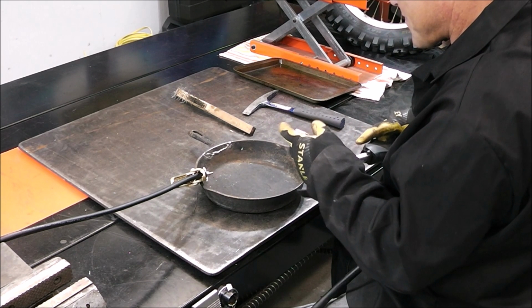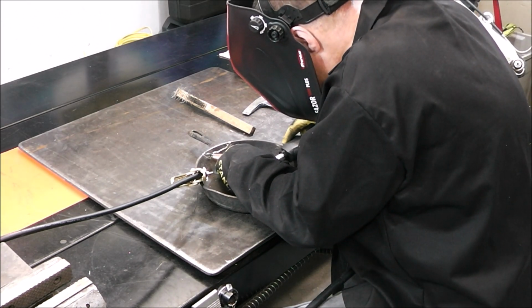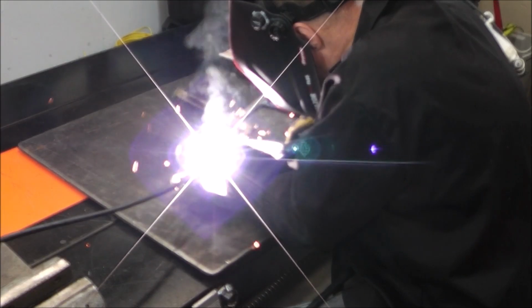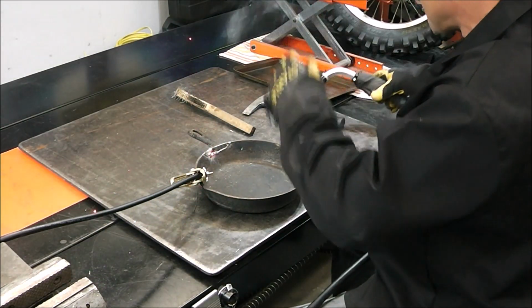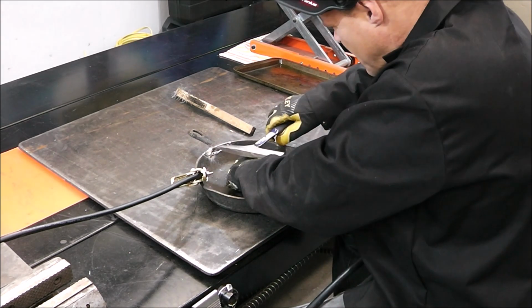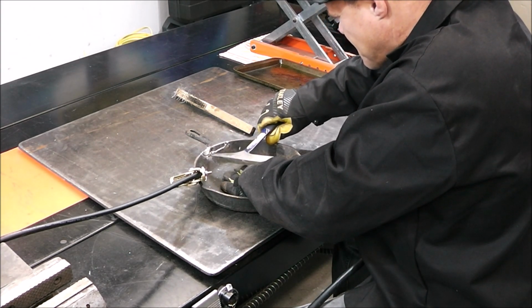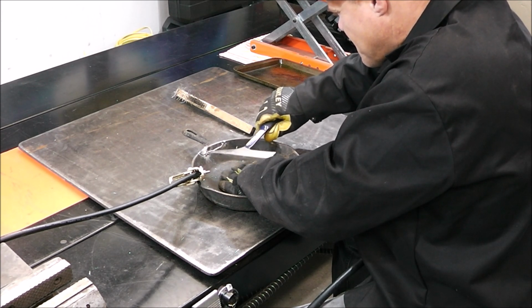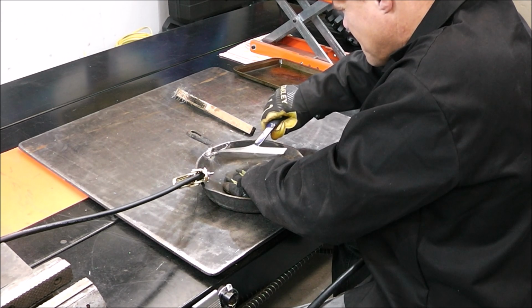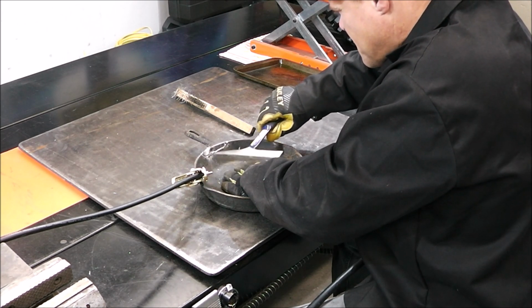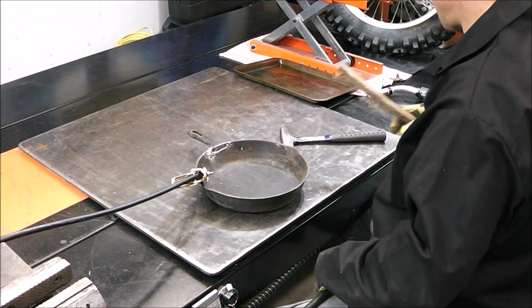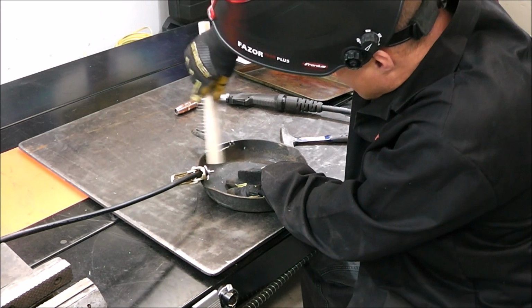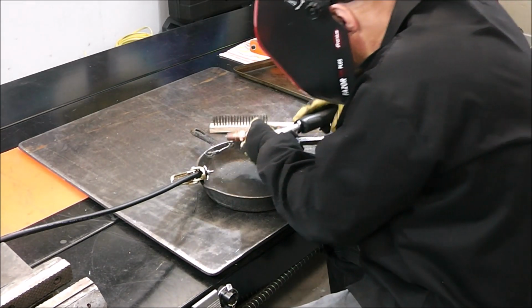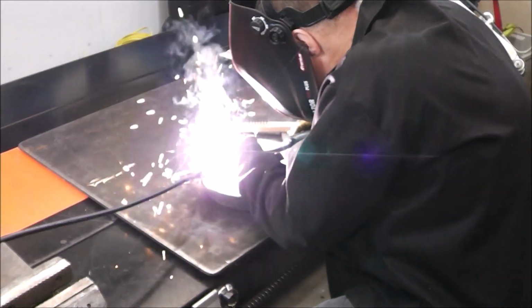I'm really liking this. So there's a few things that go on with cast iron, and I'll try to keep this kind of general, but the reason you generally try to do a preheat is because it lessens the amount of rapid shock that the cast iron has to take. If you can get the cast iron up to, say, 400 degrees, and then it's starting out from there going to a welding temperature, which is 1,000 degrees, that's just less of a temperature differential between room temperature and the temperature of what you're welding at. So it's just less of a swing. And then you do the same thing on cool down by putting it in sand or putting it in an insulating blanket.